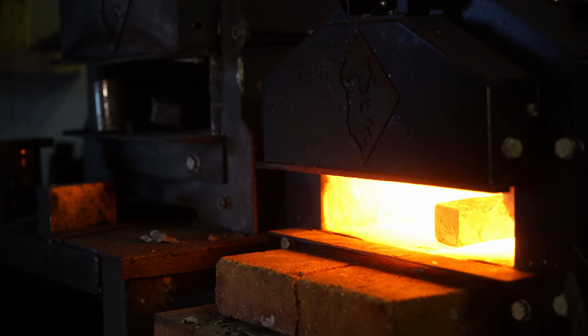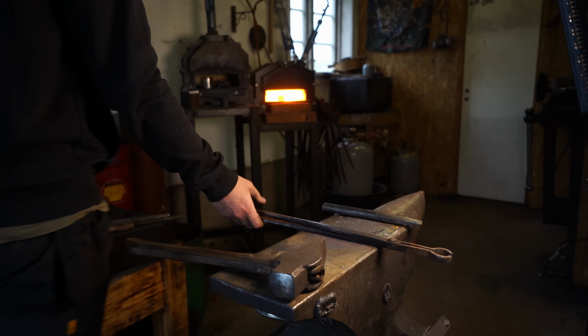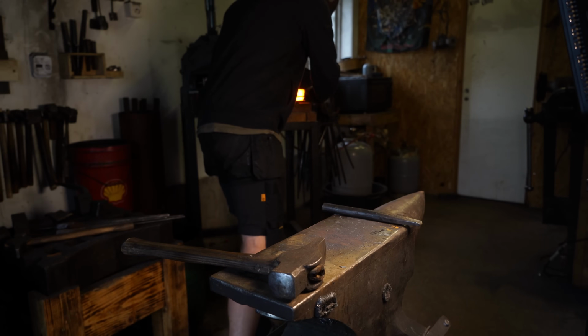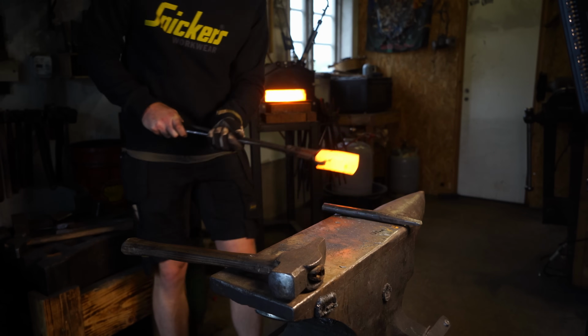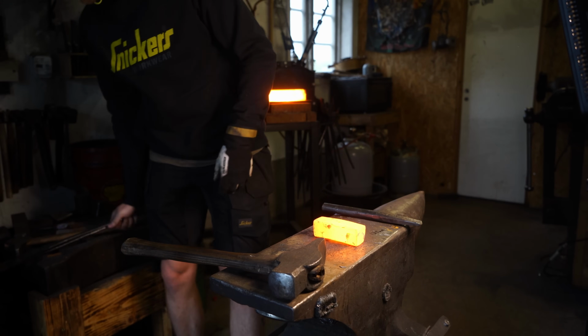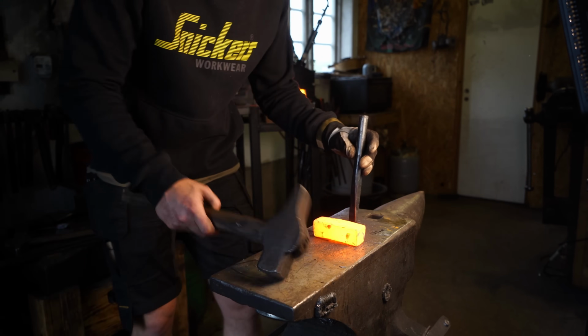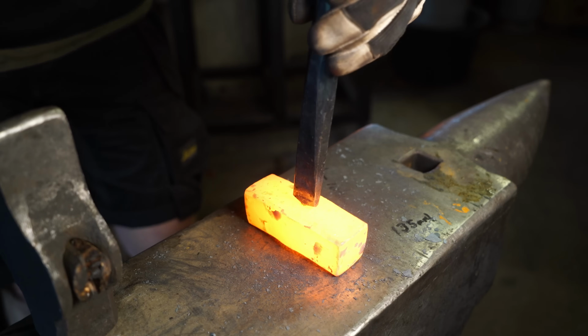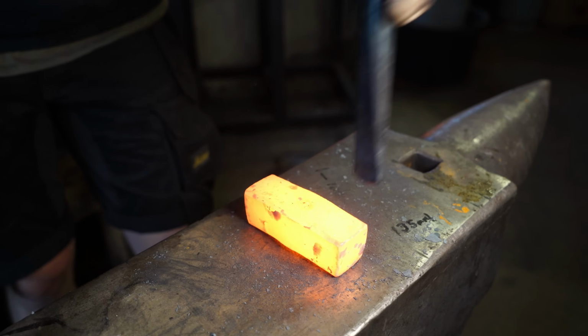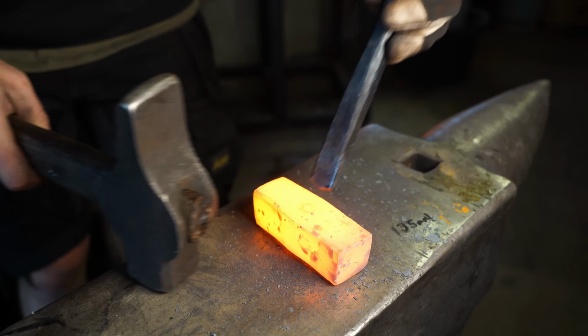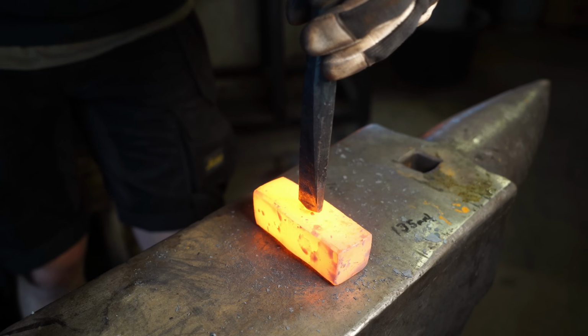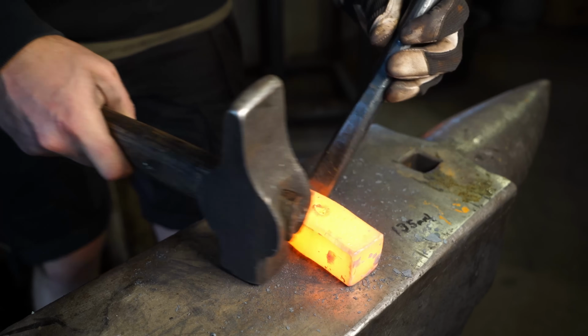So what we are doing when we're punching the eye is that we are forcing the material down on itself. When we flip the billet and start working from the other side, the two holes eventually meet, and the material that's left is then sheared off. So it's very important that the two holes are in line with each other, otherwise you might not end up with a clean hole.